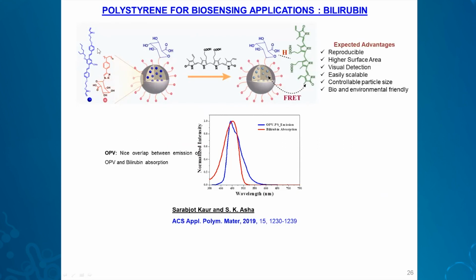So we found that this fluorescent molecule, called oligophenylene vinylene, we designed it as a crosslinker, and if that is used as a fluorophore, its emission perfectly again matches the bilirubin absorption. So this can do the job of the polyfluorene backbone in the sensing. And by miniemulsion polymerization, we have the capability to make these type of beads where the surface is decorated with the glucuronic acid.